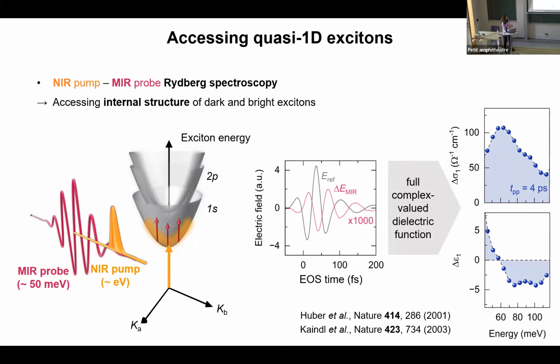And how do they appear? When we have an internal transition between excitonic orbitals, like let's say a 1s to 2p transition, this gives rise to a peak in the pump-induced change of the real part of the optical conductivity. This is essentially proportional to absorption. And at the same energy, we will have a dispersive feature appearing in the pump-induced change of the real part of the dielectric function. So with these hallmarks in our mid-infrared time domain spectroscopy, we can recognize the internal transition between excitonic orbitals.